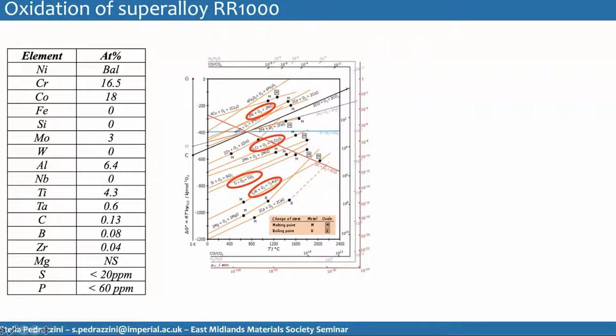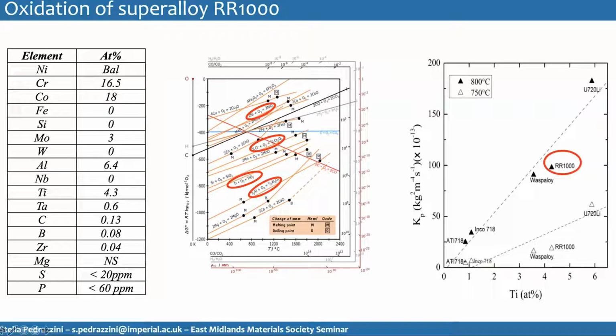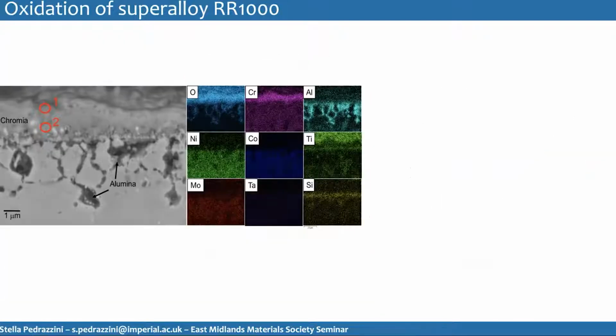And we can get an idea of where these oxides are going to form within the surface scale based on the partial pressure of oxygen that they require to form. But it's never that layered and black and white as the thermodynamic predictions would lead us to believe. And also, titanium has been shown to thicken the oxide scale quite substantially and almost linearly. So with the addition of titanium, the oxide scale thickening becomes worse in an almost linear manner.